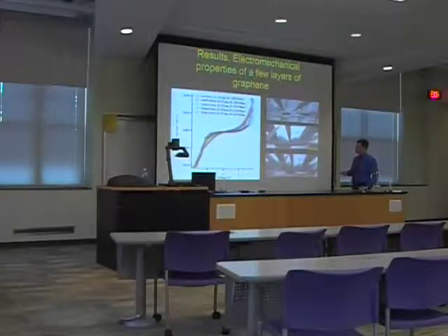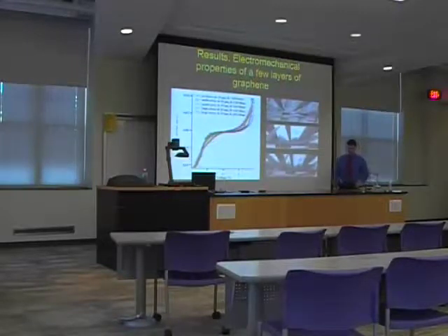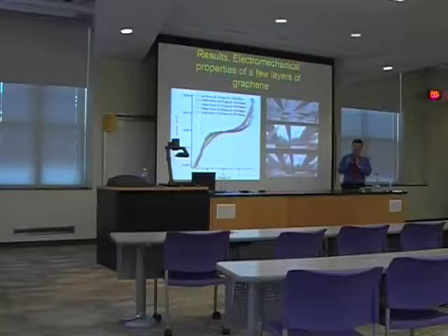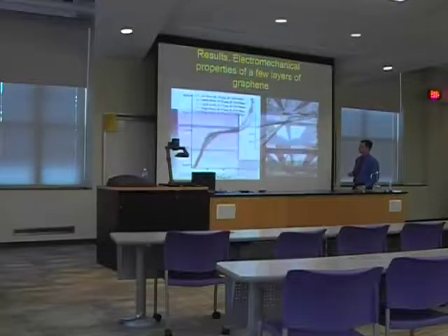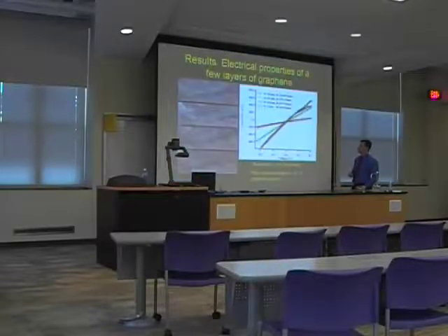So what we see in this case is, the stronger we push, the higher the pressure, the higher the conductivity. And the reason for that, from my point of view, is that you have electronic scattering between the layers, but then you squeeze them together, and your current will flow not through the top layer, but through the bulk material already, because there will be strong interaction. Scattering will be much smaller because of this compression. And that's what you see, a rise of conductivity.